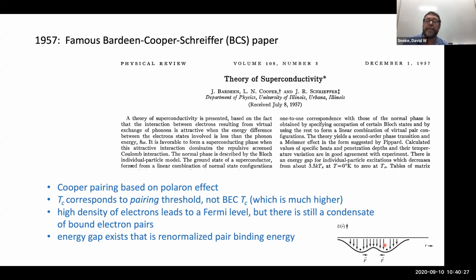The other thing that happens in a BCS superconductor is that there's a high density of electrons, and so you have a Fermi level. But it is still the case that there is a condensate of bound electron pairs. The essential physics is that you have a condensate of pairs, and I'll talk about the BEC-BCS crossover in just a second. And the famous energy gap that opens up with BCS superconductors is really just a vestige of the pair binding energy. So you have the picture of two electrons with a binding energy, and to break those apart into two free electrons, you have to pay the binding energy cost.